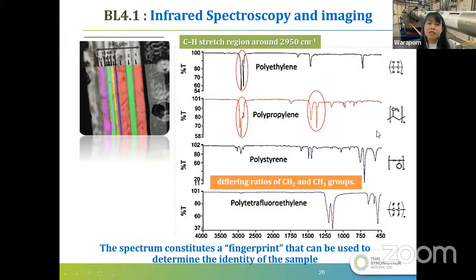And for the cross section of a thin film, like food packaging film, there are a lot of layers in the film. So we can measure one by one to see how the polymer composition differs. If you get a spectrum like this, we can use the database to do the analysis to specify what kind of polymer is in this peak. This is easier than a complex biological sample, because a polymer has only one composition.